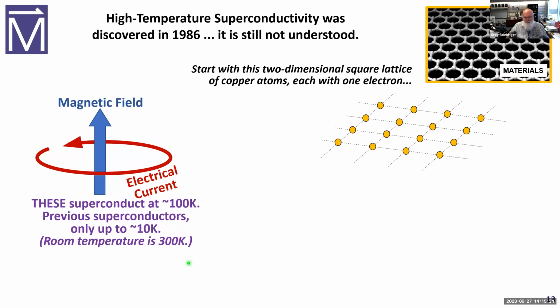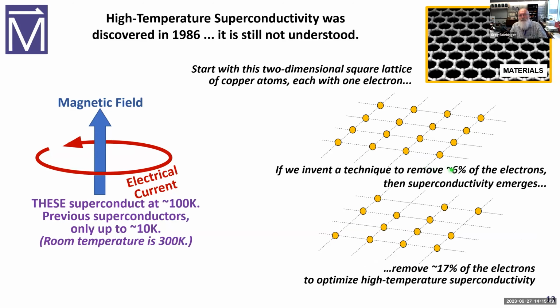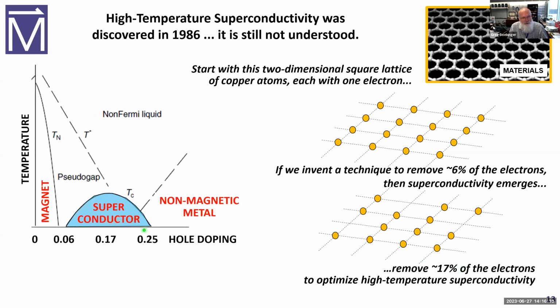Now, the first class of these high temperature superconductors to be found had something in common. And they had a two-dimensional square lattice of copper atoms, and each copper atom had one electron sitting on it. And if you invented a technique to remove 6% of the electrons, then superconductivity emerged, for reasons we don't yet understand. And if you remove 17% of the electrons in any of a dozen of these different compounds, it optimizes high temperature superconductivity. So there's a common behavior that we still don't understand about this high temperature superconductivity.